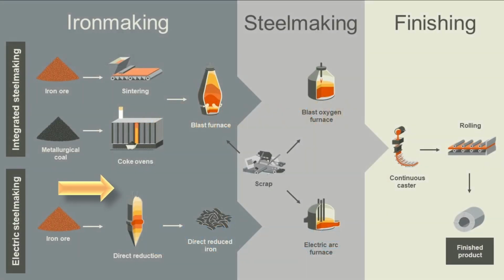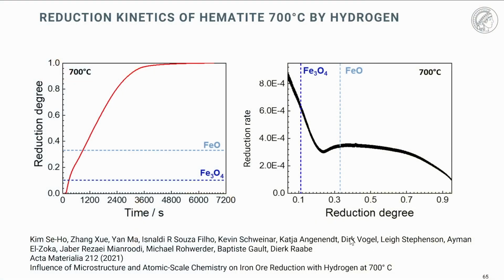So this is a typical overview of integrated steelmaking, and we only look at this part where we use iron ore subjected to direct reduction. However, we use hydrogen and not, like typically, methane gas. And from that we get iron sponge, which is then melted down in electric arc furnaces. Here we have the kinetics at 700 degrees centigrade under hydrogen atmosphere. First you see the very fast reaction rate from hematite to magnetite and from magnetite further to wüstite. But as soon as you get into the wüstite reduction state, and the wüstite is then further reduced towards iron, you see that the reaction becomes very sluggish and becomes slower and slower as you go along.